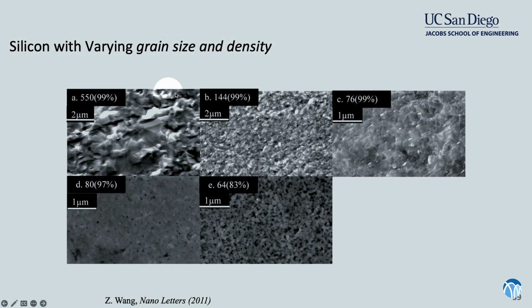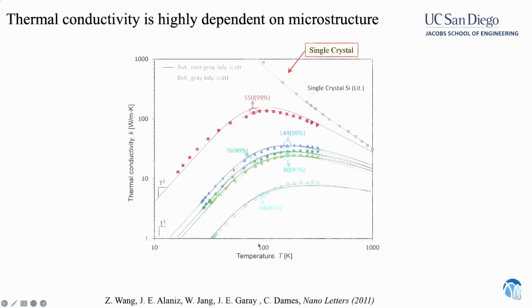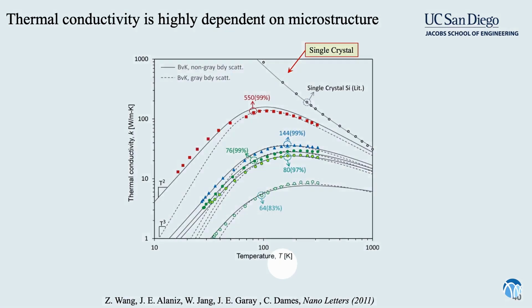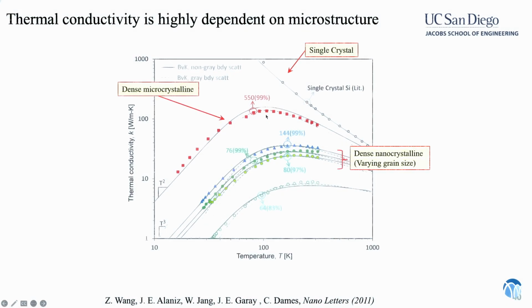So here are some micrographs just to show you some data. These are some materials that are made. This is silicon, all silicon with large crystal sizes. Here to small crystal sizes, and these are materials with voids in them, right? Like the voids we were talking about before. So now if I plot that same plot, thermal conductivity versus temperature, the data I showed you before, considering just the crystal structure, is way off the chart here. The material with the real microstructure, the thermal conductivity is much, much smaller.